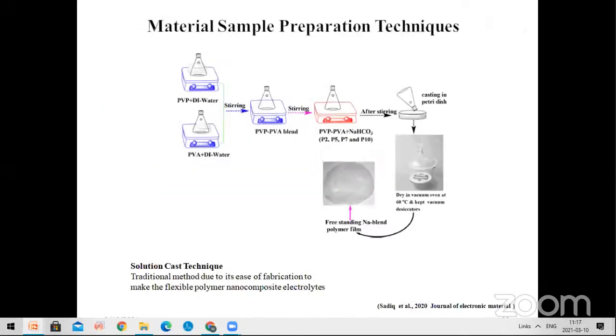This is how to prepare the polymer electrolytes. First, we take the host polymer PVP with some DI water and stir for a few hours, and then add another polymer, PVA, doping it into the PVP and stirring for 1 hour. Finally we get the PVP-PVA blend, and then we can optimize different weight percentages and concentrations of the salt, stirring again for 6 to 7 hours. Then we take it in a petri dish for vacuum oven drying, and finally we get a freestanding polymer electrolyte film.